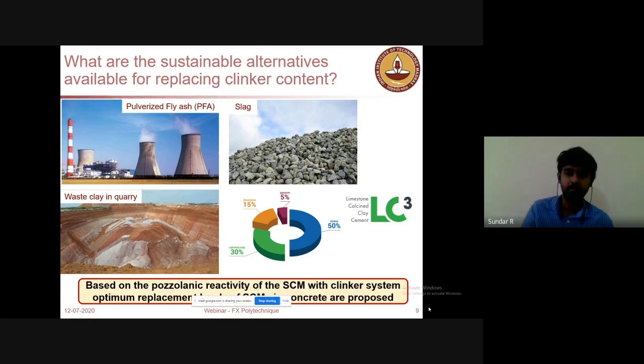So the pozzolanic reactivity of the SCM, that is how much reactive silica and alumina it has. If you go back and look at the chemistry of the cement, you will see calcium, silica, and alumina are the three major elements which are going to react and form the binding product. So the presence and the proportion of the reactive silica and alumina in these SCMs are the governing factor for deciding how much optimum replacement can be used. That has been researched a lot.